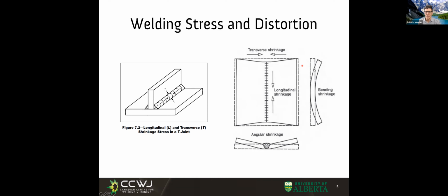This is the plate seen from the side. And this vertical direction here is the lengthwise direction of the weld. And if the weld is on top, we would have more force on top than in the bottom, and we will end up with a plate being a banana. This distortion in particular, this bending shrinkage, is the key type of residual stresses in additive manufacturing of metals.